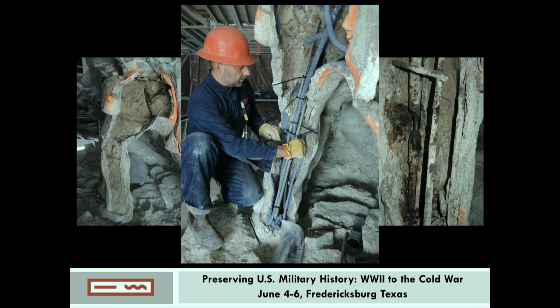Lapping extended to approximately 12 inches in each direction where feasible, and the new fiberglass rebar were lapped with existing rebar in adjacent areas of the sculpture for maximum continuity. All replaced rebar were assessed by structural engineer Craig Bennett to ensure that they were correctly attached and structurally sound. We were concerned about that because we could not open all of the sculpture, so sometimes we had to lap onto pieces that were already there, but we made sure that those pieces were not to be replaced. They were fine. Nothing was lapped onto something that looked like in the future it might have kept corroding. But of course that's a concern of ours because we didn't open the whole sculpture.